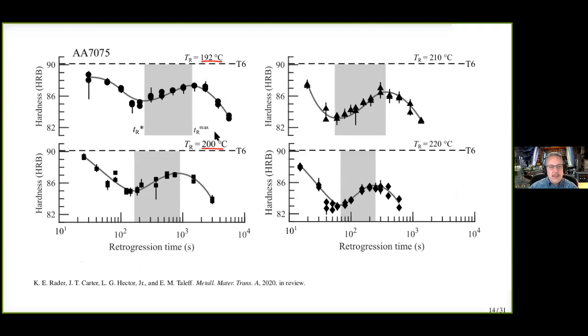So what you will see at the 8 degrees Celsius higher temperature of 200 is that the TR start time has moved to shorter times, and the TR max time has moved to shorter times. So by going to higher temperatures, we're accelerating the retrogression process. This continues at 210 and 220. Now, at 220, we get a little bit of contraction here, so something else may be going on. We have the general trend that increasing temperature decreases the time necessary for retrogression to occur, both at TR start and TR max measures. So how do we predict this?